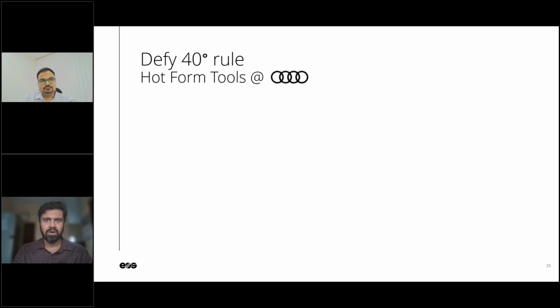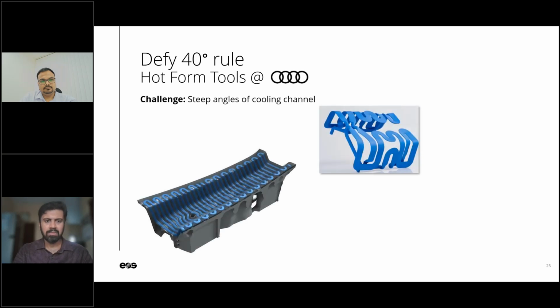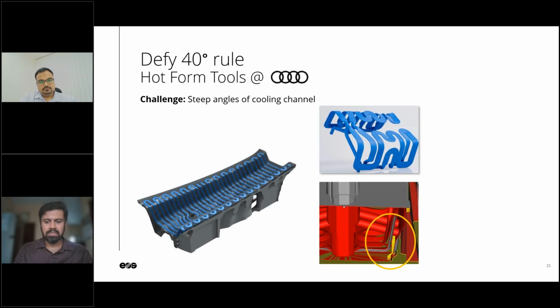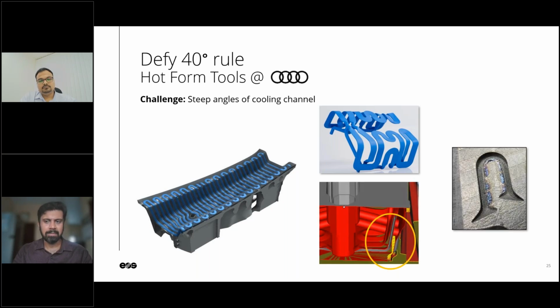Now this was a hot form tool for the A4 cars in Audi, and this is how the tool is, and they wanted to have such a conformal cooling circuit designed for this tool. Now if you see, it's almost horizontal, right? And if we have to have this channel almost horizontal, basically a pocket almost horizontal, there's going to be enough issues on heat such that you have a burnt mark such as this, right? What happens is when you have such burnt marks, the surface is very, very poor, plus the buildability is lost.